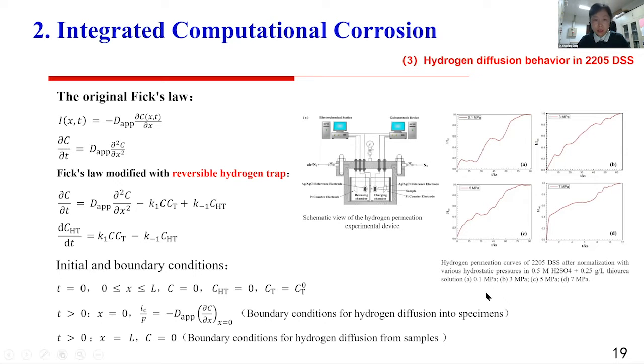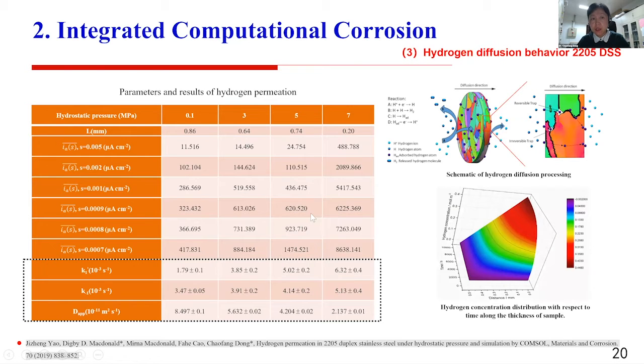This task was carried out by Professor McDonald and Professor Mirna. We tried to use the original Fick's laws to establish this equation, and also use the reversible hydrogen trap to modify Fick's laws. After that, we did a lot of tests with the parameters and the results of the hydrogen permeation. This is from the experiment.